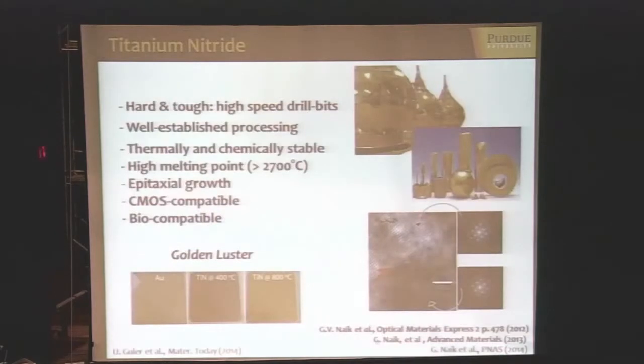Most importantly, you could easily grow this material epitaxially, so you have single crystal quality through a very simple deposition method, such as magnetron sputtering. To have single crystal quality for gold and silver is an absolutely heroic effort—it's extremely hard. Normally you get island formations and a polycrystalline structure instead.